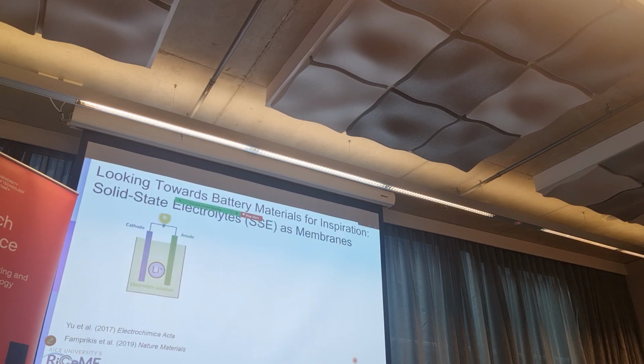We see a nice correlation where selectivity roughly correlates with the difference in binding energy. This tells us that if binding energy is tailored correctly, and if you can synthesize a membrane with well-controlled binding sites, it would be a good approach for separation.